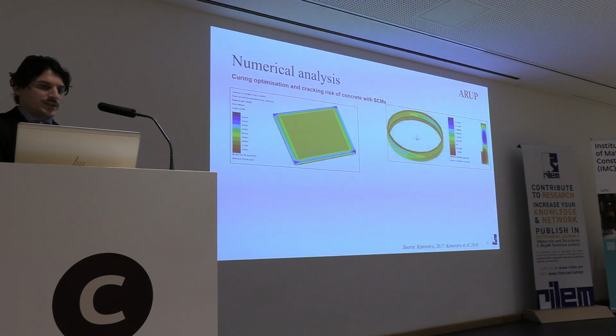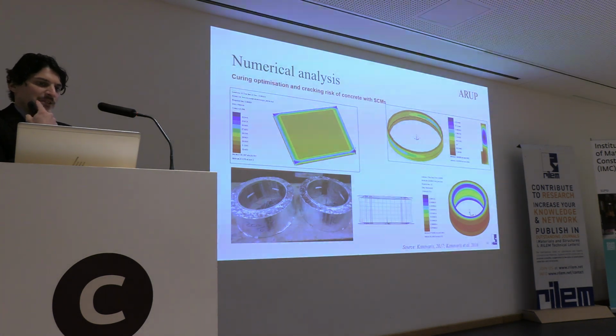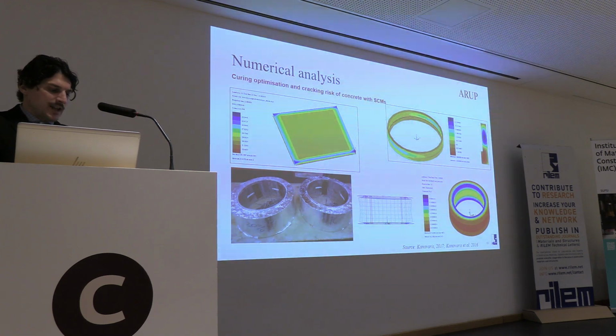semi-massive and massive concrete structures, and also taking this further into autogenous shrinkage studies, and with different supplementary cementitious materials. We employed restraining devices. This is the typical ring test, and with modeling, we investigated how efficient slag actually is in mitigating this type of cracking phenomena. We found that at certain high temperatures, the efficiency of slag might not be as high as anticipated in terms of reducing the cracking risk, because of some increases, for example, in autogenous shrinkage and the decreased tensile strain capacity.